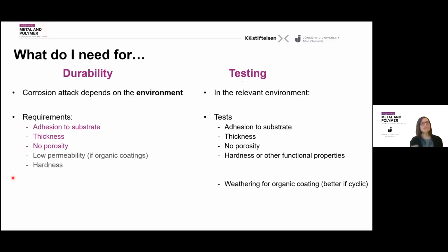Those requirements are not so much on the final coating choice, but on the adhesion to the substrate, the thickness you want to apply and the capability of having that thickness everywhere, and the capability of the process to avoid defects and porosity. Check the permeability and weatherability if you work with organic coatings, and of course choose a material with the hardness you need.